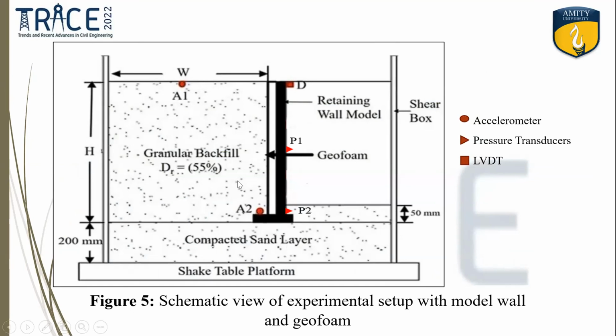The first step of the experiment is to prepare the compacted sand bed up to the height of 20 centimeter. After that, various sensors are used such as accelerometer, pressure transducer, and LVDT. Two accelerometers were attached, one at the base of the retaining wall and one at the top of the backfill material. Two pressure transducers are attached, one at mid height of the retaining wall and second at the base of the retaining wall.